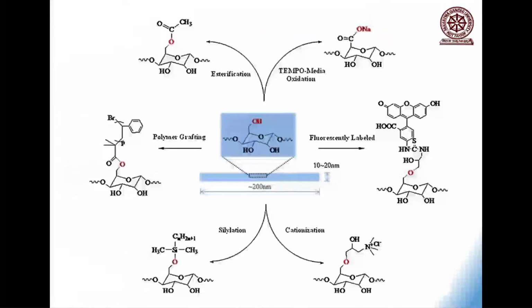There are a lot of chemists here. After making nanocellulose, dear friends, you can do a lot of chemistry on the surface. You can do esterification reaction. You see, this is nanocellulose. You can do TEMPO-mediated oxidation process, and you can see OH could be converted into COOH. You can introduce fluorescent labels on the surface of nanocellulose for sensing. You can graft polymers on the surface of nanocellulose. You can do silylation reaction.